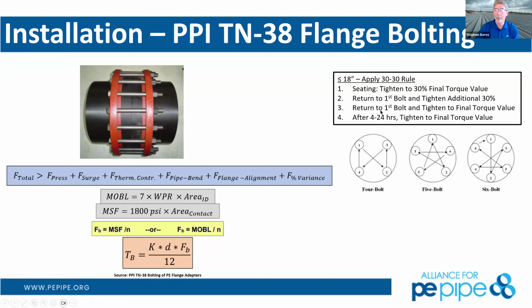So this is just an example. If you're doing less than 18-inch pipe, you do the 30-30 rule. You're going to tighten at 30% of the recommended torque value, and that's to seat it all. Then you're going to start with the star pattern. You're going to go to the first bolt and tighten an additional 30, go around to all the bolts and do that. Then you're going to go back to bolt one and tighten it the rest of the value. Now, the last step is you're going to let that sit for 4 to 24 hours for it to relax and get to its final state. And then you're going to come back and do one more final torque to that torque value again to fully seat everything and make sure that you have a nice tight joint.